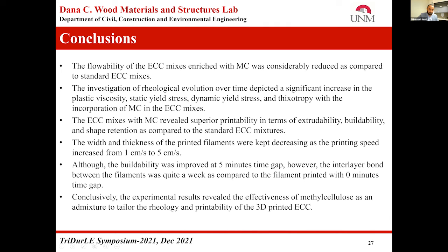And when we evaluated the effect of printing speed, we increased the printing speed from 1 centimeter to 5 centimeters. The width and thickness of the printing filament kept decreasing as we increased the printing speed. But when you introduce the time gap between the printing layers, it could be 5 minutes, could be more, the buildability was improved, but the interlayer bond strength between the filaments was quite weak and the porosity was also increased. That could affect the mechanical performance of the filaments.